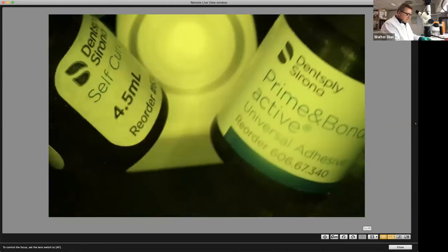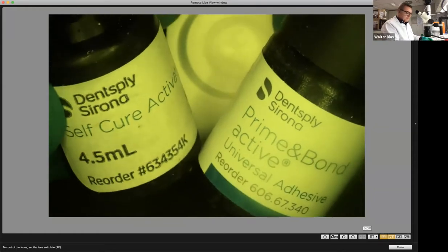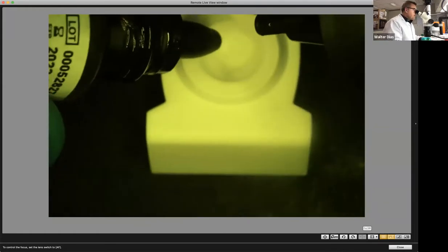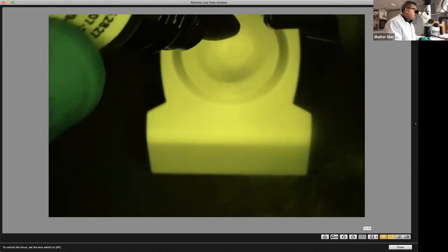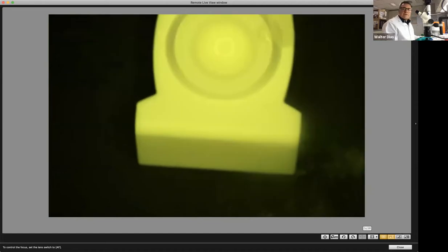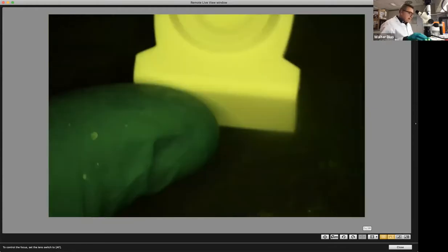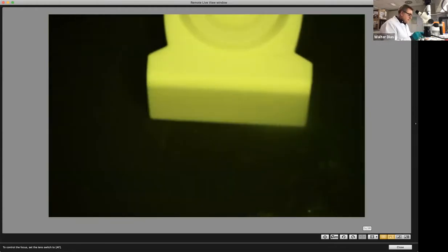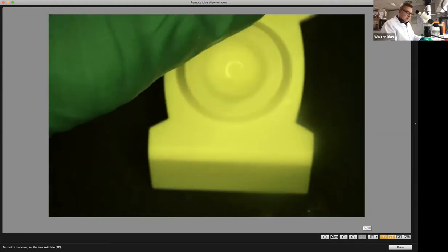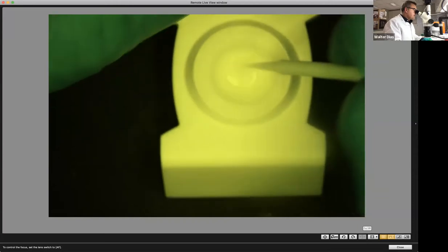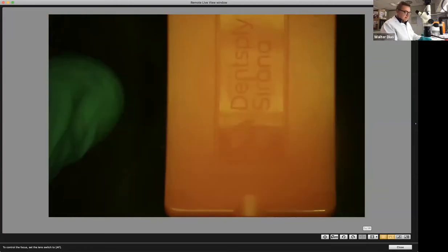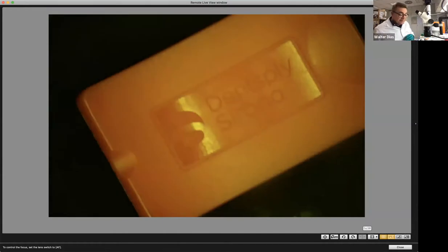So now we're gonna get a Clix dish here. And we're gonna mix the adhesive and the self-cure activator in equal parts. The self-cure activator kind of activates the adhesive. Yeah, so equal parts, one drop of each. It activates the adhesive so the adhesive can cure together with the cement. This is what it does, okay? So you put one drop of each, you mix it for 5 seconds. This Clix dish is really good because now you can close it and this can hold up to 15 minutes, sorry.